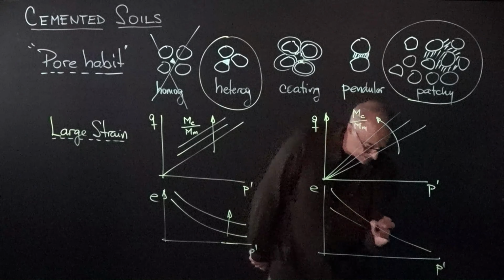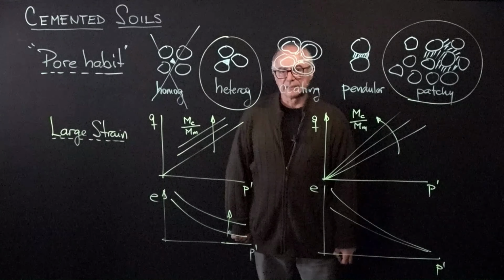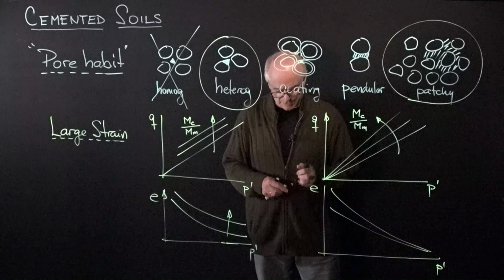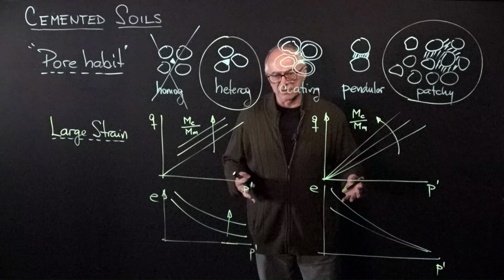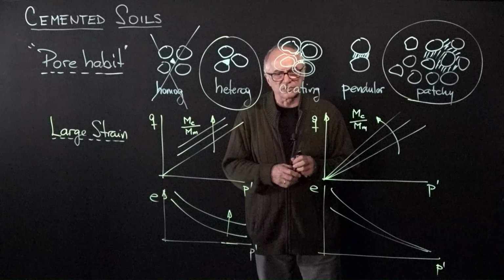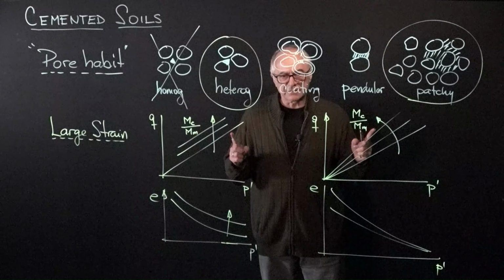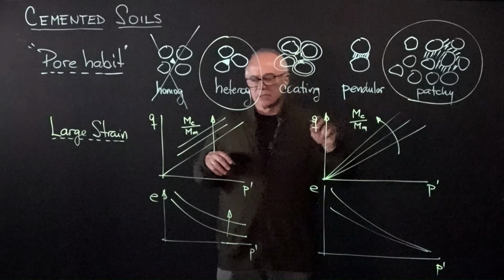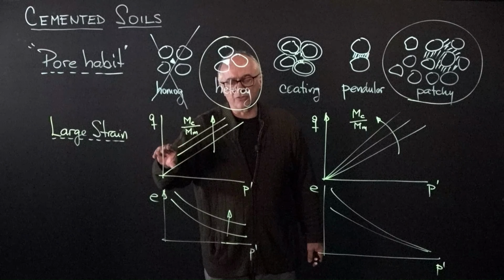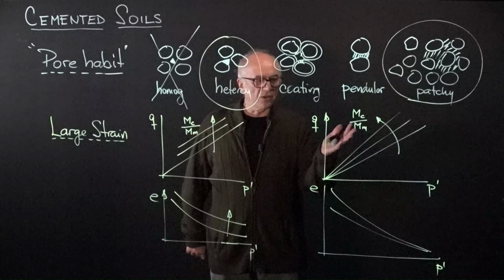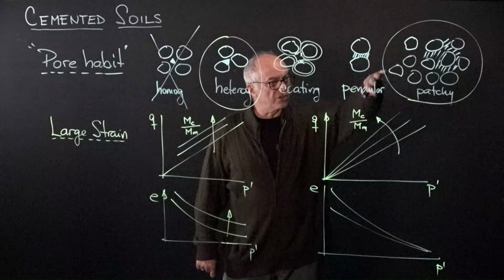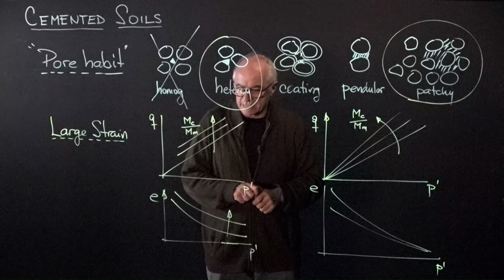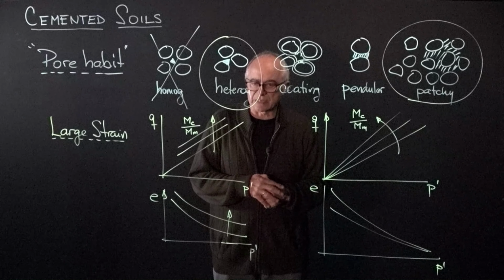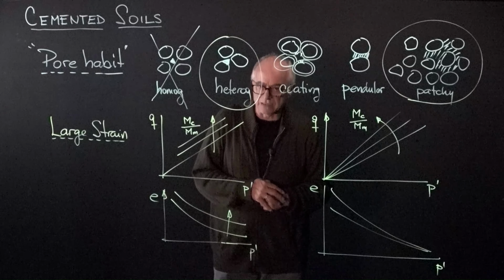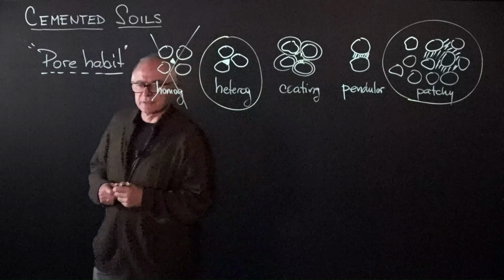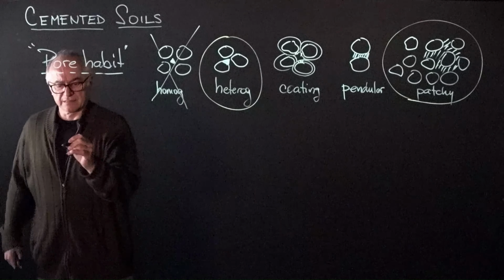as similar lines probably converging at very high P prime, which is probably the case for all these situations. This has been explored with discrete element methods for fairly constrained geometry, so it deserves further analysis. But there is a take-home message. As we increase cementation, we may increase this effect of cohesion at the intercept, but we may also cause increasing friction because of the tortuosity of the shear plane. And in both cases, there will be increasing dilation, so there is a shift in the critical state line towards higher void ratios. The other parameter that cementation affects is permeability.